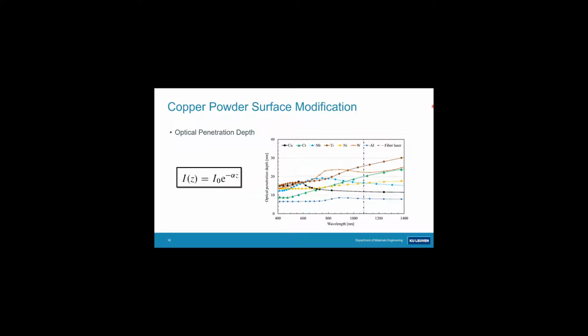Now, further elaborating on the idea of surface modification of powder particles, we were first thinking about how deep such a laser beam actually interacts with the material, and it's not deep at all. So you see that the optical penetration depth calculated using Lambert-Beer law for different materials is in the tens of nanometer range for many materials. So that would basically mean if you modify the outer few 100 nanometers of a powder or of a solid substrate, you would already see a significant effect.